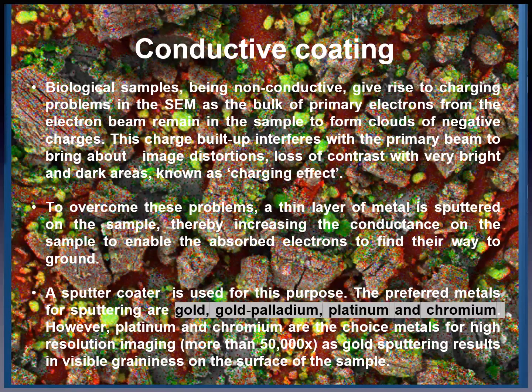Biological samples, being non-conductive, give rise to charging problems in the SEM, as the bulk of primary electrons from the electron beam remain in the sample and form clouds of negative charge. This charge build-up interferes with the primary beam, bringing about image distortions and loss of contrast with very bright and dark areas, known as the charging effect. To overcome these problems, a thin layer of metal is sputtered on the sample, thereby increasing the conductance of the sample to enable the absorbed electrons to find their way to ground. A sputter coater is used for this purpose.